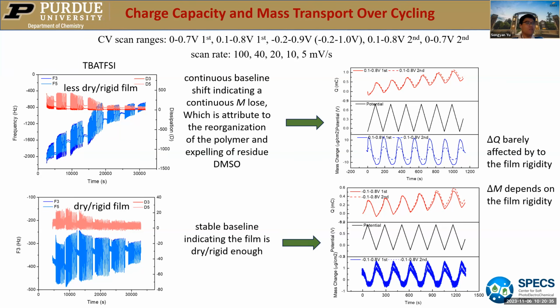So the mass transport behavior can also be different. I just zoom in, taking one cycle at one scan rate and at one potential range. A good sign is that we can see the charge change. It doesn't matter whether I pick the CV from several hours before or several hours later; the charge change is basically the same. So I did many hours of cycling, but the charge capacity keeps stable, both in the less dry film and the dry film. But the mass transport can be different.